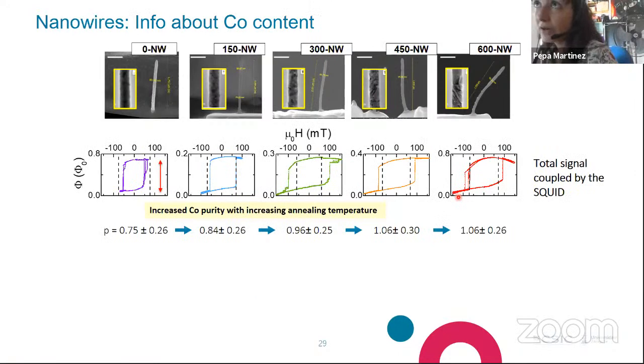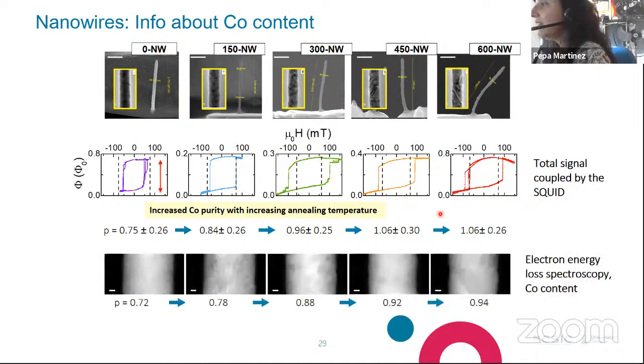We measure these nanowires using our NanoSQUIDs, individual nanowires. Okay, these are some examples. Well, these here are some hysteresis curves obtained at 4 Kelvin for individual nanowires annealed at different temperatures. The first thing we could tell is that the purity of these composites indeed increased. We could tell so because we can estimate the amount of magnetic material in our measurements by comparing the total signal captured by the SQUID with numerical simulations. As you see here in these numbers below, the purity, this P, of these composites indeed increased up to almost 100%. These numbers agree very nicely with experimental measurements performed by electron energy loss spectroscopy. Okay, you can compare these purity values with those obtained by this technique here below.